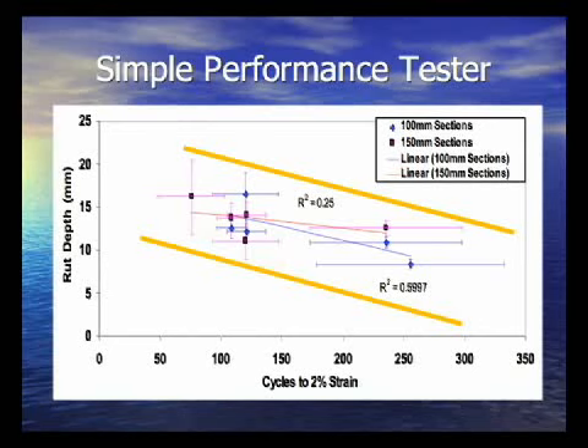When we look at the number of cycles to 2% strain in the repeated load test, and we compare that to rut depth, it depends on how you interpret that. If you look at straight crude numbers of R squared, it's going to tell you one story. I don't think we should be using this type of correlation for such small data points. I think when you look at the trends of these, you actually see a trend, and I think that's a better story.